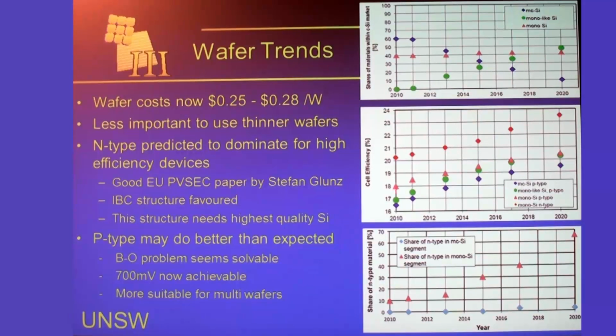So if you look at the efficiencies they predict, this is what they're thinking will happen with the N-type mono wafers. At the moment, they're around about the 20 to 21% efficiency. They're expecting that to go up to above 23% efficiency by 2020. On the other hand, if you look at the P-type Czochralski, that's at the moment at something like about 18 to 19%, close to 19%, and it's expected to saturate at around about the 20% level.